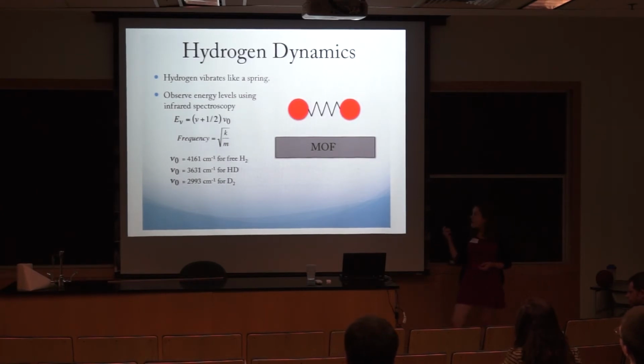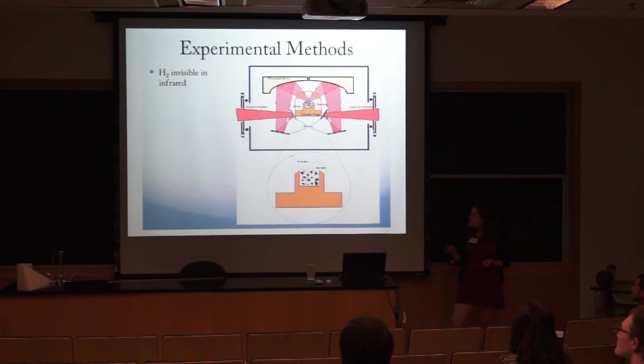So you can see that hydrogen has a different frequency than deuterium, since deuterium has a proton and a neutron, versus HD, so a hydrogen atom bonded to a deuterium atom. And furthermore, the MOF also changes the vibration, so we can figure out what the binding energy is by how much it changes the spring constant, basically.